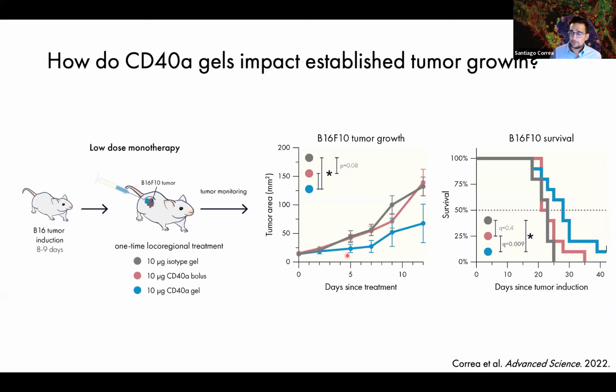Based on that, we wanted to confirm that we are going to see improvements in efficacy. And for that, we turn to this B16F10 melanoma model, which is famously resistant to immunotherapy. We treated these mice 1 time with our hydrogel or a local bolus of CD40 and just saw how that would affect tumor outgrowth. And we saw that when we administer this drug with a hydrogel, we can slow down tumor growth, and we see a moderate but significant benefit in overall survival, where now around 10% of our mice would generally end up as long-term survivors.